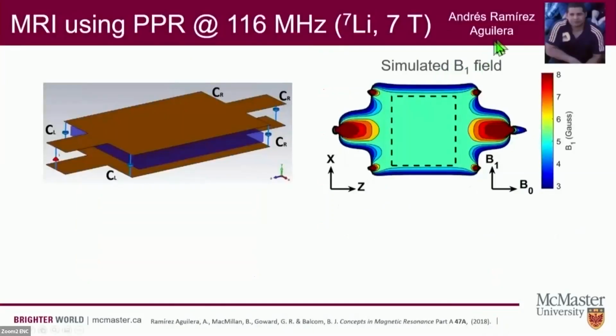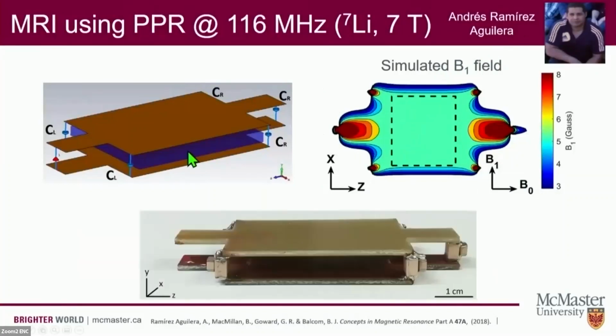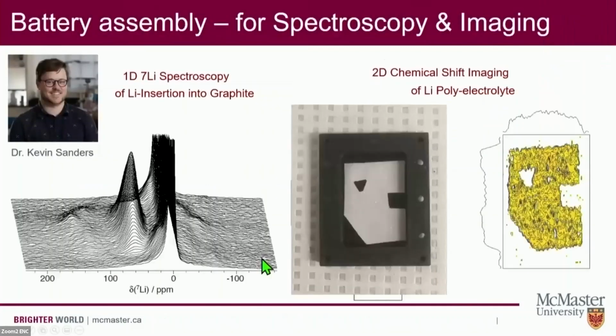So this is Andrés from the Balcom group. He did the simulations of the B1 field in that device. And this is what the device looks like in practice. What we do is slip a cartridge cell lithium ion battery within this parallel plate resonator to determine different properties of the cell. This is now the work of Kevin Sanders, who's a current postdoc in our group. And he was able to use this cartridge cell geometry to do both spectroscopy and imaging. This is the image of a polymer electrolyte using chemical shift imaging. So you can see that this tool is going to become quite robust.